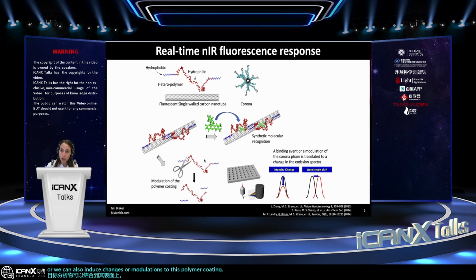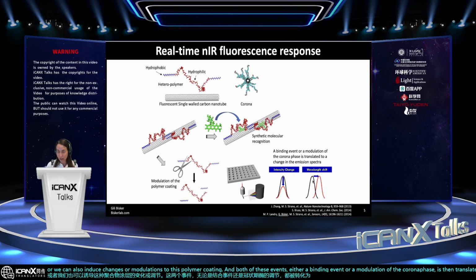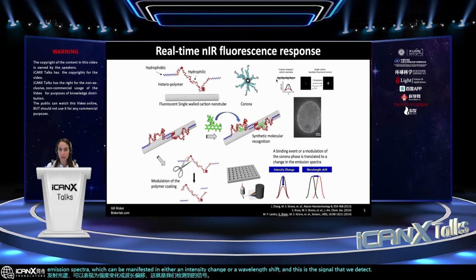And both of these events, either a binding event or a modulation of the corona phase, is then translated to a change in the emission spectra, which can be manifested in either an intensity change or a wavelength shift. And this is the signal that we detect. For example, this is a functionalized nanotube with functionalization that is sensitive to dopamine. Dopamine is a small molecule neurotransmitter. And upon the interaction with dopamine, the intensity increases.